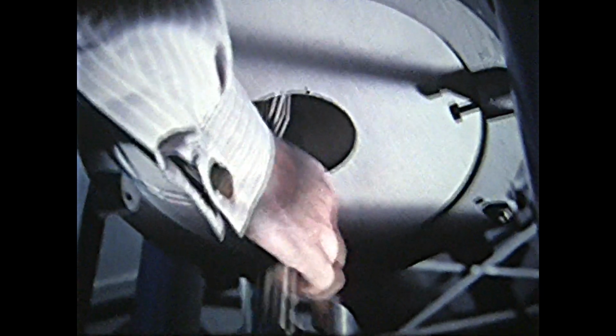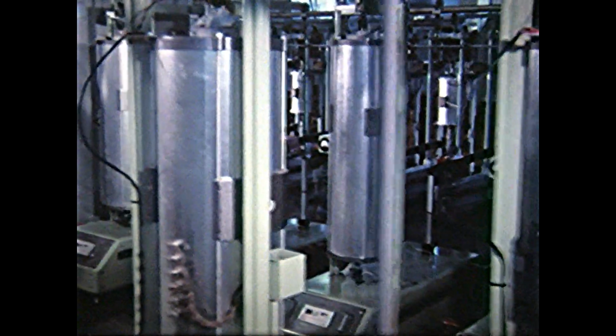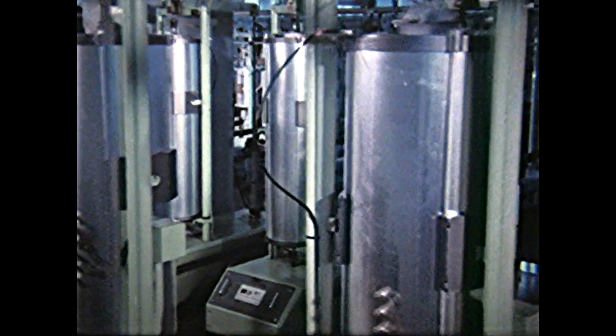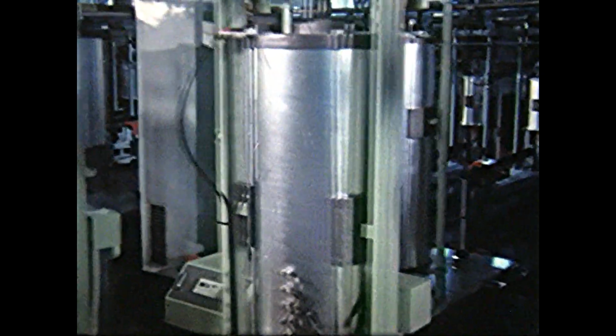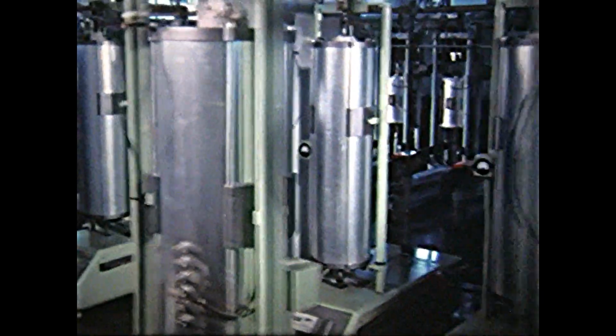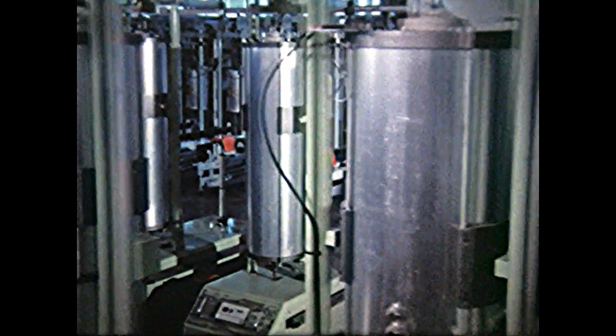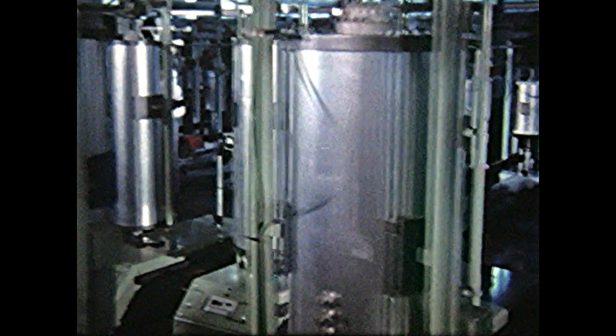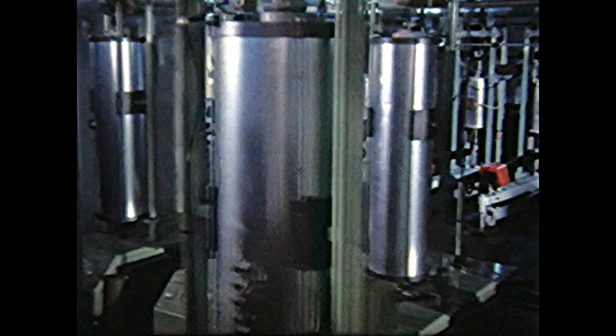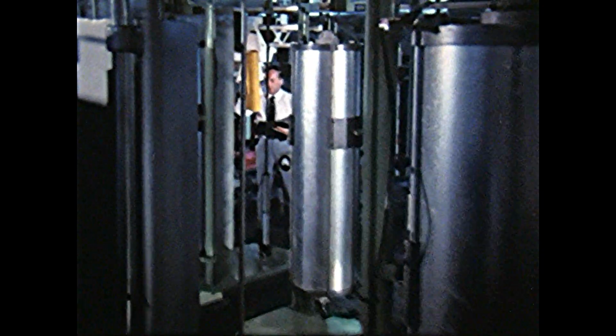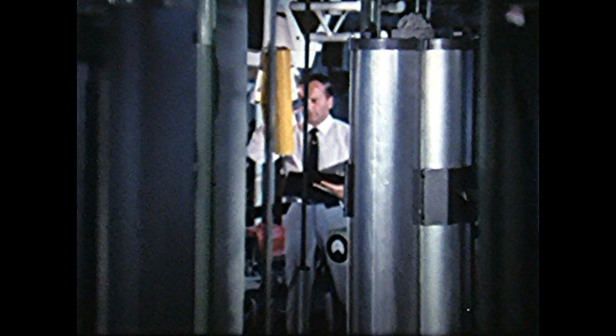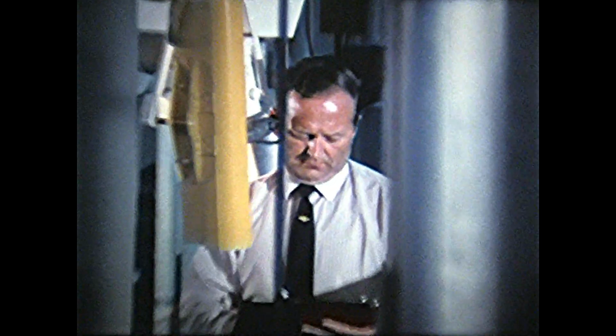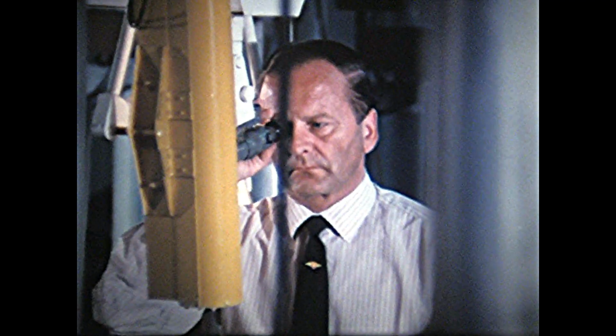Tubes for steam superheaters are another critical power station component. They have to work at red heat. At this creep test laboratory, inside these banks of heaters, hundreds of different steels are being tried out for the next generation of power stations. Steels with different metallurgical structures, steels made by different methods. Some of the test pieces have been at high temperature under heavy load for as long as 15 years. A telescope and mirror system enables elongations of a few millionths of a millimeter to be observed.